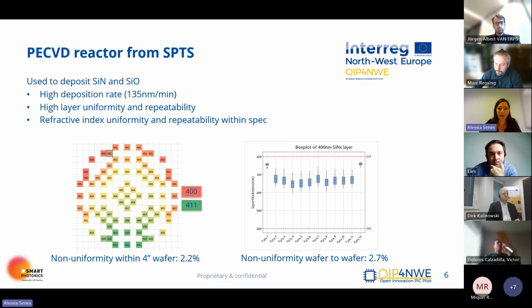The second tool that has been bought and installed in the project is the PECVD reactor from SPTS. This is used for dielectric layers, in particular silicon nitride and silicon oxides. It gives high deposition rates, 135 nanometers per minute is what we can use. It gives a high layer uniformity and repeatability. And also the refractive index uniformity and repeatability is within specs. So at the beginning of the project, we set some specs for the different tools, and these specs have been achieved for this reactor.